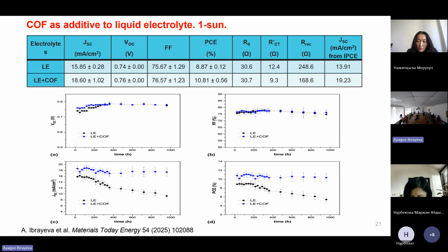Thank you for this question. I think that it helps us in both cases. In general, it works as a scaffold, prevents leakage and reduces charge transfer resistance. And by the Tafel analysis, we can say that there was a higher exchange current density, a faster oxidation of iodide to triiodide, and COF materials help us suppress recombination in general.